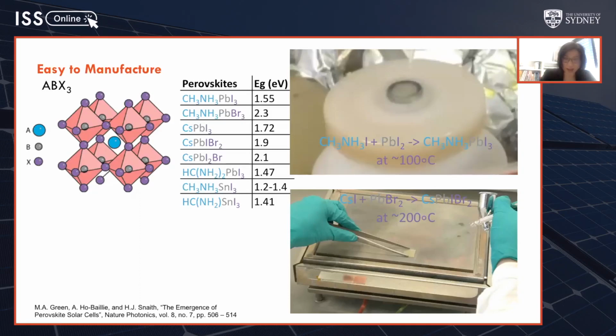So if you remember, a silicon cell has to go through hours and hours of high temperature process for purification and then crystal growth and slicing. With perovskites, on the other hand, it can be done using solution process. So simply by mixing the organic halide salt with metal halide salt, put it in a solvent and you can deposit it on the substrate. So the first video shows how you can make methyl ammonium lead iodide thin film by spin coating that precursor solution on the substrate.